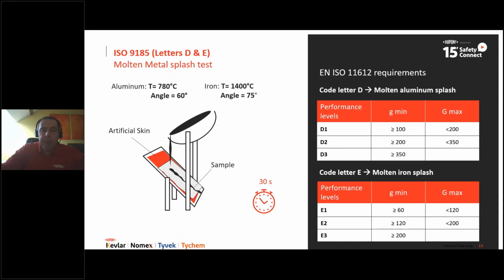your material, you have failed level D2, but you have successfully passed level D1 before, and that's why the definition of D1 is more than 100 grams of molten aluminium, but less than 200 grams of molten aluminium, because that would equate to level D2 already. And the quantities for iron may be different, but the principle is exactly the same. And you see the different performance levels on the chart.